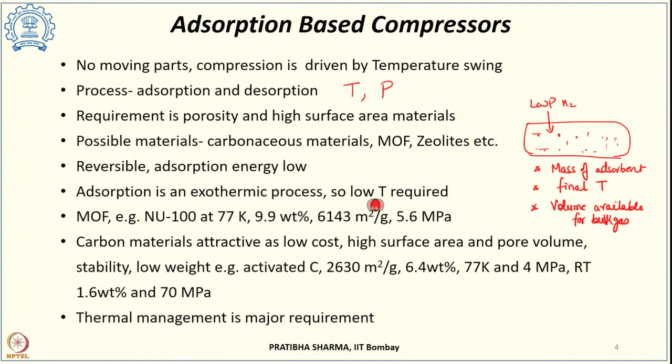The interaction involved in adsorption is a weak Van der Waals interaction, and the thermal motion energy can be of the same order of magnitude as the adsorption energy. So we need to cool down the system to get sufficient adsorption. Unlike metal hydrides where a strong chemical bond is formed as a volume phenomenon, here adsorption is a surface phenomenon forming a monolayer on the adsorbent, requiring low temperature. This can be economically achieved at liquid nitrogen temperatures.